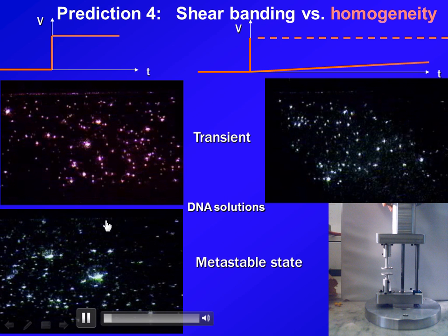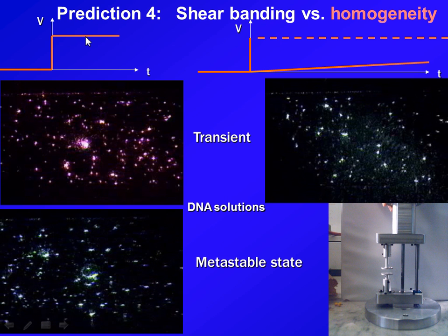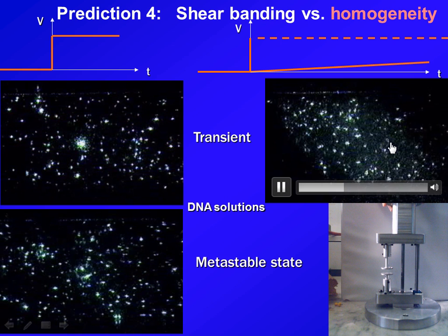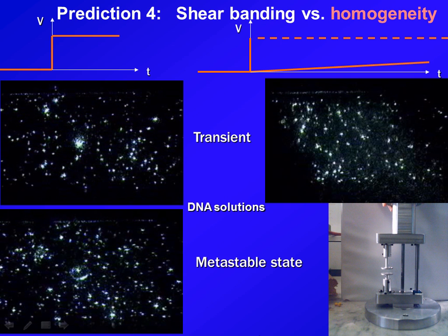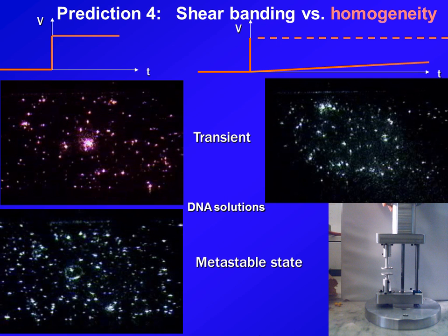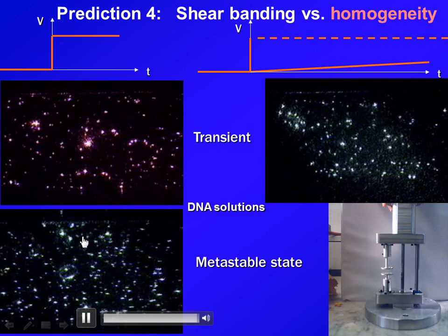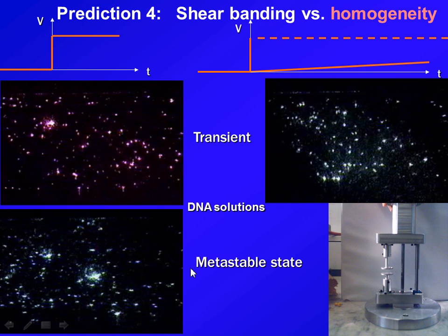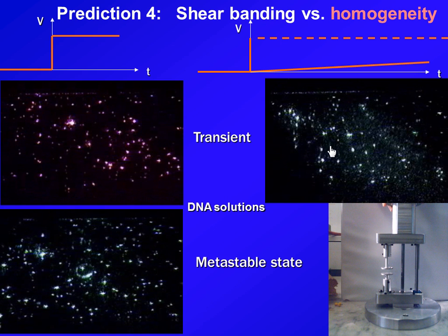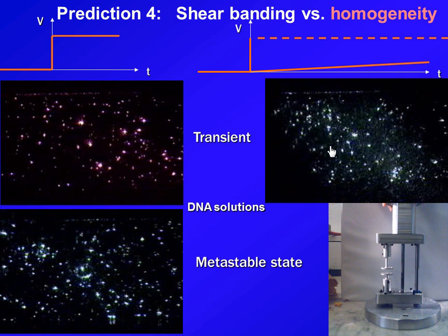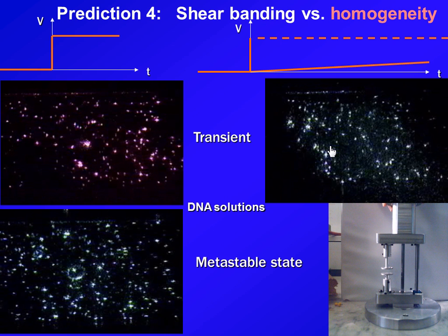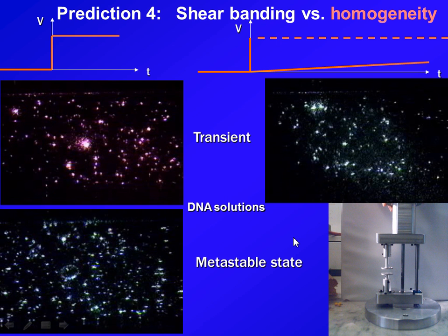So this is the steady state if you abruptly apply the shear versus you infinitely slowly apply the shear. This is very troubling conceptually. Depending on how you impose the shear, despite the fact your final external boundary condition is the same, you end up having very different rheological states, as you can see. And that's very hard for theory to treat, to think about. All the constitutive theory, particularly integral equation type theory, would think there is a memory term.